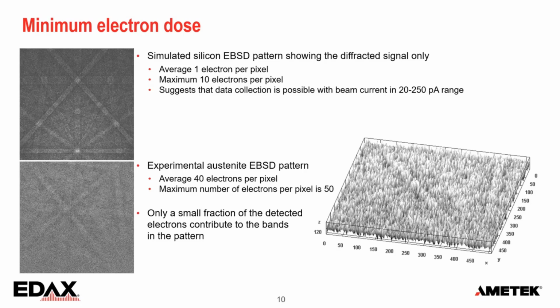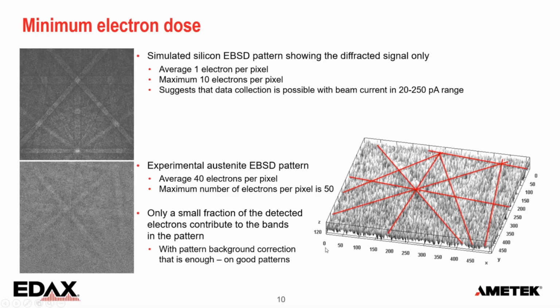And when we do a background correction and we look at the pattern intensity, you can see a lot of noise, and we can just make out the bands in this three-dimensional plot that I've made of this particular pattern. But it's enough. So when you have good diffraction patterns, this is very indexable.